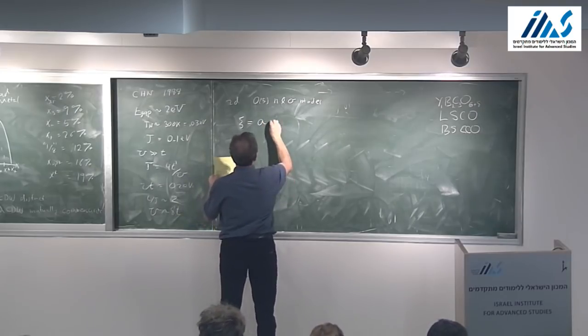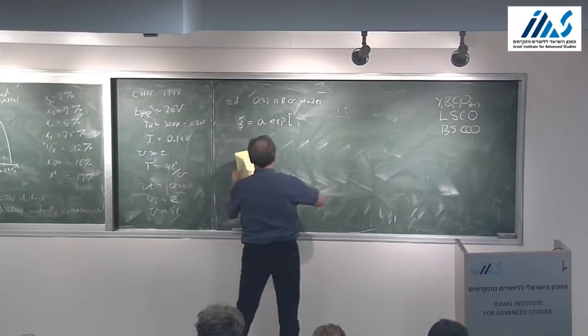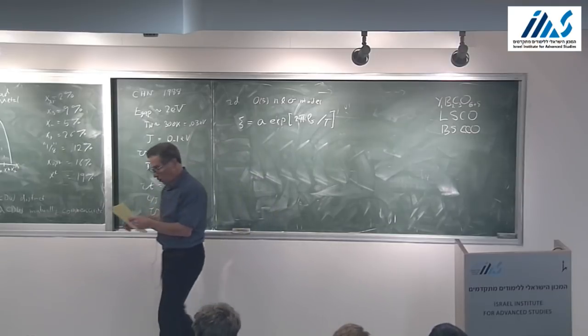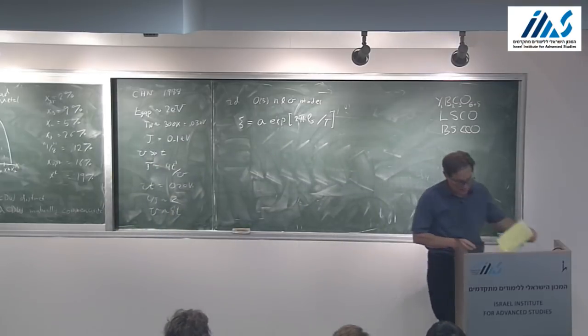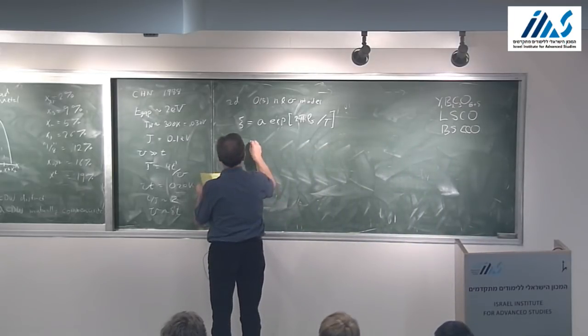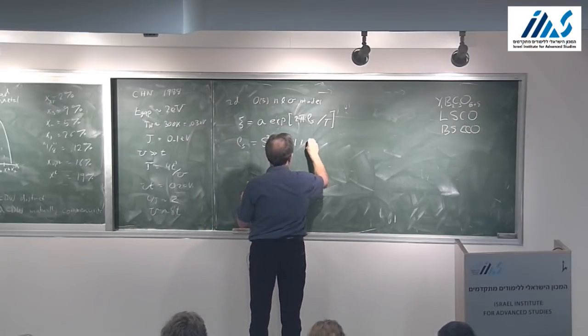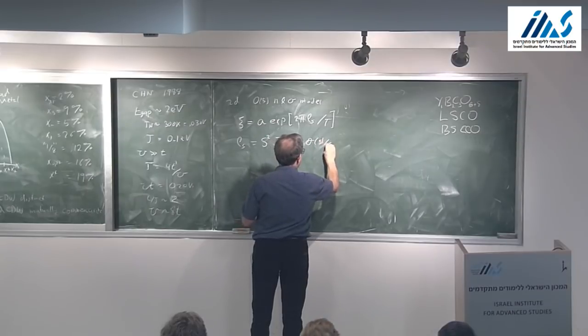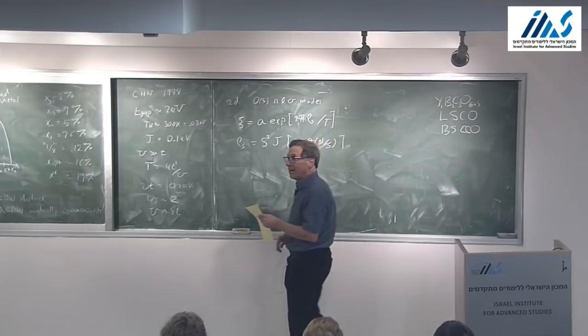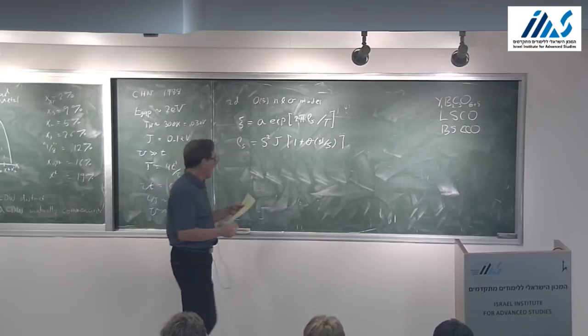For this, we can calculate what the correlation length is, for instance, and other correlations. So of this form, where rho s is the renormalized spin stiffness, one can imagine trying to calculate rho s from microscopics, say for the nearest neighbor spin s. There's some expansion. They did this to some order in 1 over s, and then plugged in s equals a half, and get something like 0.15 J.